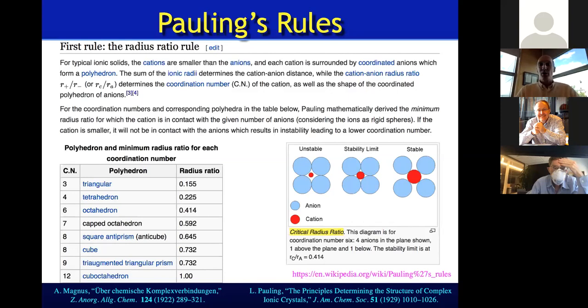And so what's stable here is when you've packed as many anions, those are the blue things, around a cation as possible. What's listed as unstable is when these spherical anions are overlapping, so now you're starting to get a lot of repulsion from these anions. You want to have the Coulombic attraction between the cation and the anion, but not that repulsion. So the stability limit, and Pauling worked this out for a bunch of different coordination polyhedra, including in perovskites the all-important octahedron, is what the radius ratio should be between the cation and the anion. And from Pauling's first rule, what we learned in synthesis is that the stability limit is when you just have the anions touching each other.